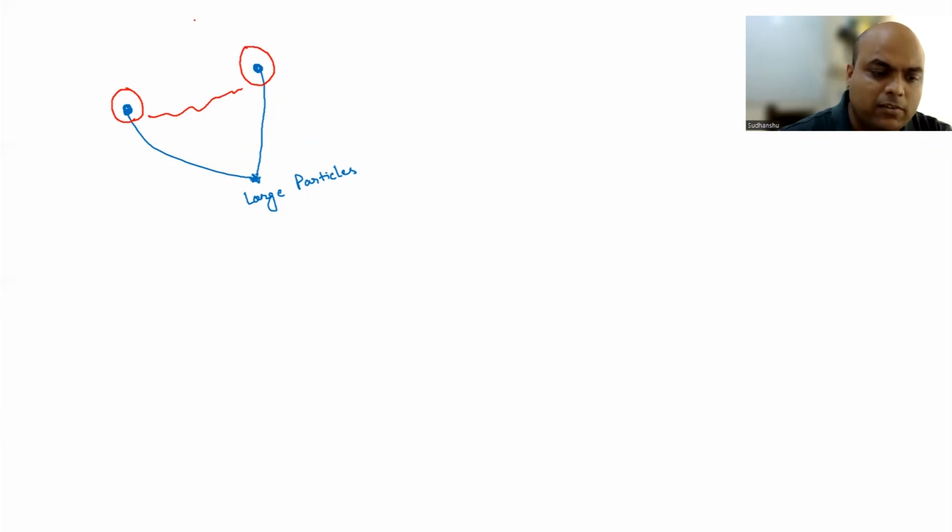So now what will happen? Now suppose you have smaller particles, a distribution, like something like this. Okay, so now because of the strain localization, you can nucleate voids. So previously these particles were not contributing towards void nucleation, right? Now because of the formation of voids in the larger particles, now you can nucleate voids in the smaller particles.